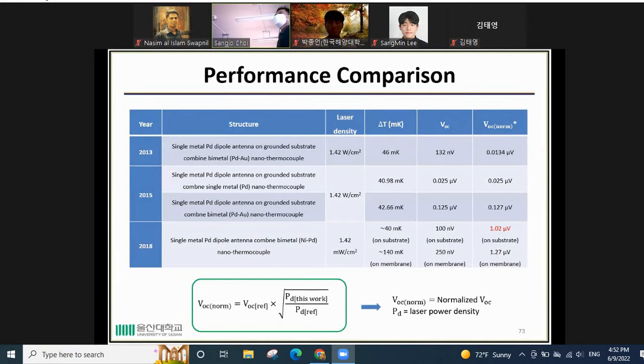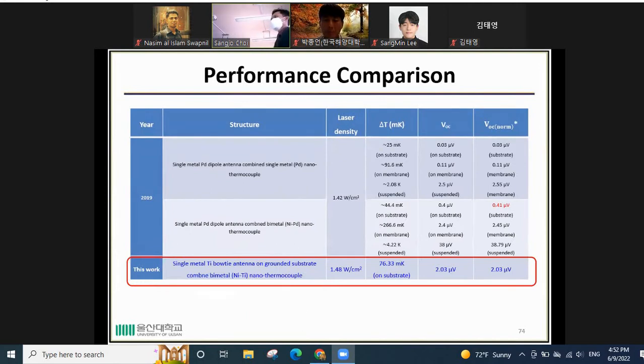And this is the performance comparison of the VOC between our structure and other reported structures. We use the VOC normalized of the nano antenna. This is the equation to calculate the VOC normalized. And compared to the other structures, our proposed thermoelectric nano antenna is showing higher VOC with the same structure, which is the nano antenna mounted directly on the silicon substrate.